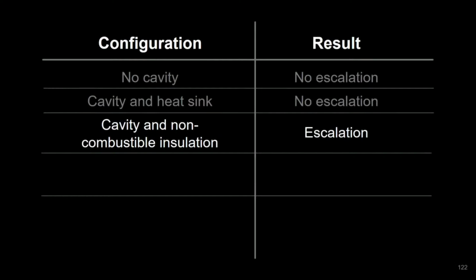When this non-combustible insulation product was used, I found that escalation occurred. That is, the Reynobond PE became fully involved in the fire. I consider this to be a very interesting result. It suggests that the insulation product did not need to burn in order for an escalation to occur. It was sufficient that the insulation product allowed heat to be retained within the system.